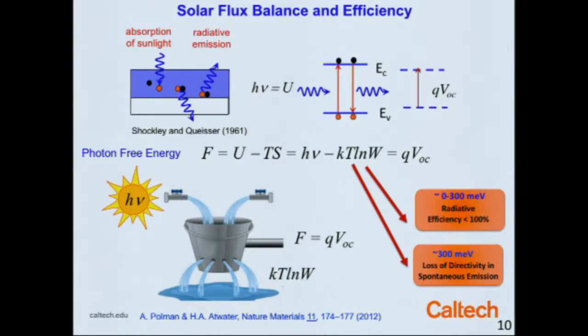When sunlight is absorbed in the solar cell, generating charge carriers and giving rise to radiative emission, that emission is now isotropic. So we've increased the number of photon modes, and the number of directions, which is equal to the number of modes in a ray optic view. That necessarily accords with an increase in entropy. So simply the change in the directional distribution of sunlight actually results in a voltage loss. It's a very fundamental thing.